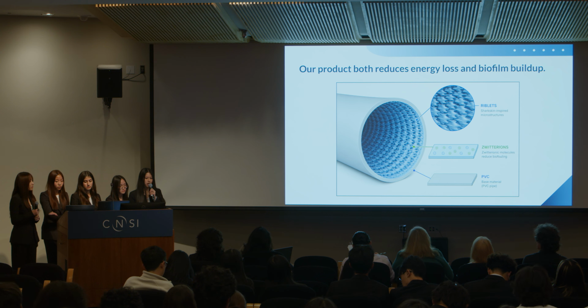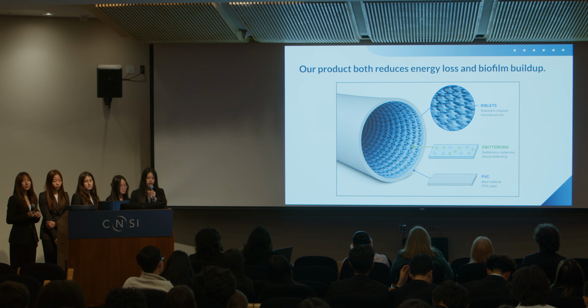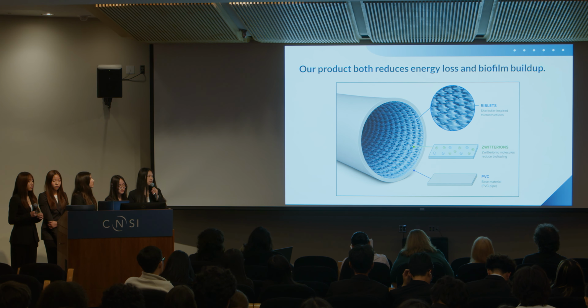The inside surface of SharkPipe contains microscopic riblets inspired by shark skin. These grooves are aligned with water flow and reduce drag by reorganizing the turbulence that occurs near the pipe wall. This means that pumps then use less energy to move the same amount of water.